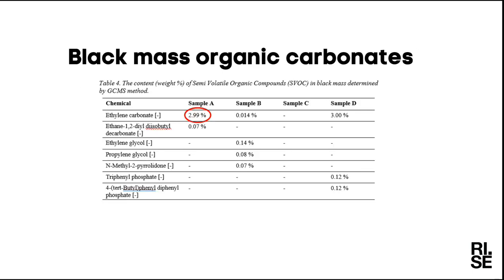And also we analyzed the organic carbonates, which is the main composition of the electrolyte in the batteries. Some of the carbonates have a higher boiling point, which cannot be completely evaporated during the production of the black mass. For example, sample A has some content of ethylene carbonate, as well as sample D, and B has very little, and C not detected. Because of these organic carbonates, they are very flammable and will increase the risk of fires and explosion. So it's important to understand the content in the black mass.